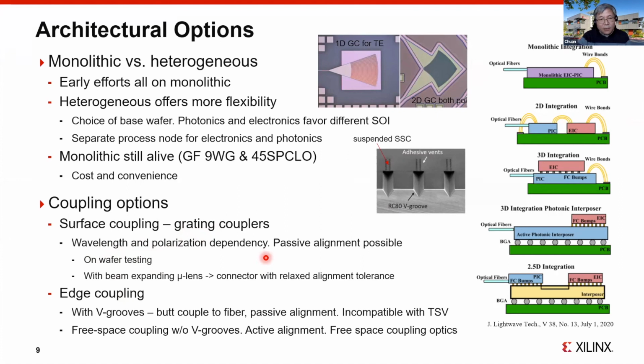And grating couplers are polarization dependent. So if you know the polarization, you can use a simpler one-dimensional grating coupler. But on the receiver side, your incoming polarization can be TE or TM or a combination of the two. So you have to use the 2D grating coupler, and 2D grating coupler usually has higher loss. But one big advantage of surface coupling is it facilitates on-wafer testing, because you can have optical access through the grating couplers.